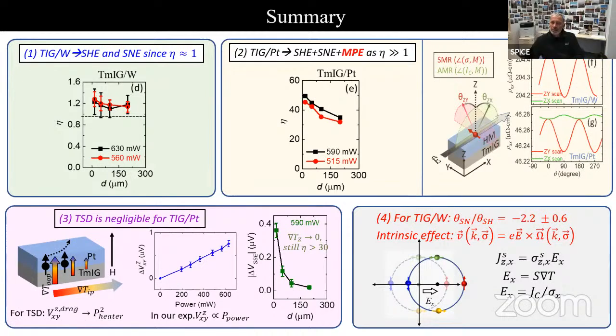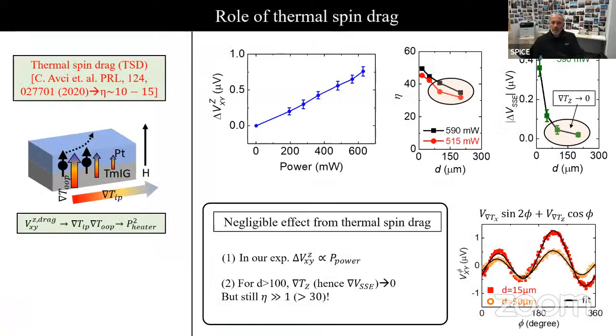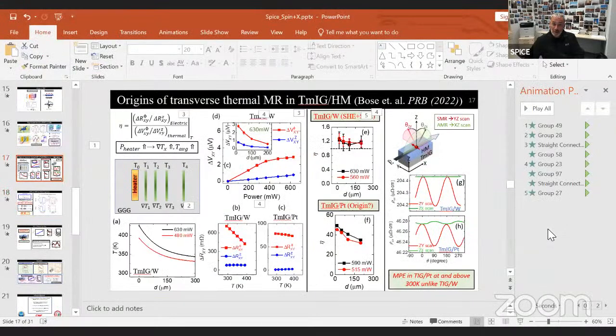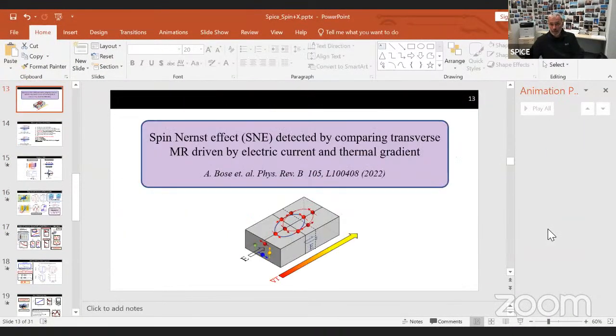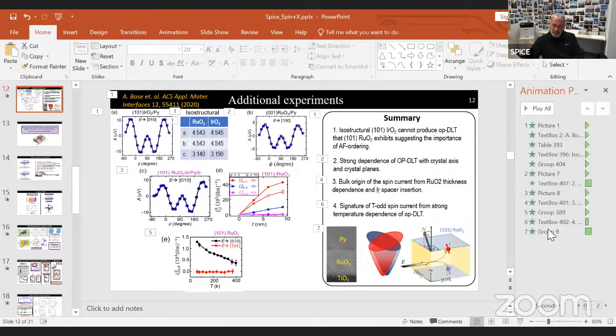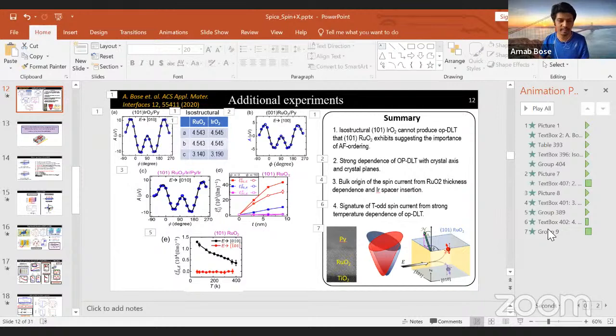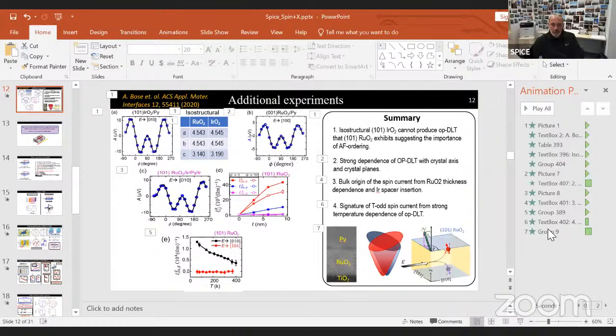Okay. And in relation to the spin splitter experiment, do you have a mechanism in mind for how you would be able to switch the Néel vector in order to test this? Right now it's suggestive that this is the origin, but it's not fully tested from that perspective. Yes, that is something we had in our mind, but we could not eventually do it. So yeah, that is a really good thing to check. One possibility could be annealing the sample in the presence of a magnetic field during the growth. Something like that may help, but I'm not exactly sure how to control the Néel vector. I'm not sure if that would favor 180 degrees. Yes. Maybe coupled with a gradient or something.